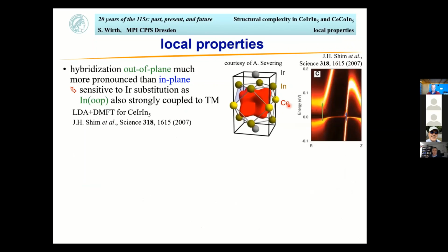This is again work by Gaby Kotliar's group that has been mentioned several times already. And he pointed out that the out-of-plane hybridization, meaning now the cerium is at the center, the iridium is up here, that the out-of-plane hybridization here with the indium is much stronger than the in-plane hybridization. Yes, like this one here.